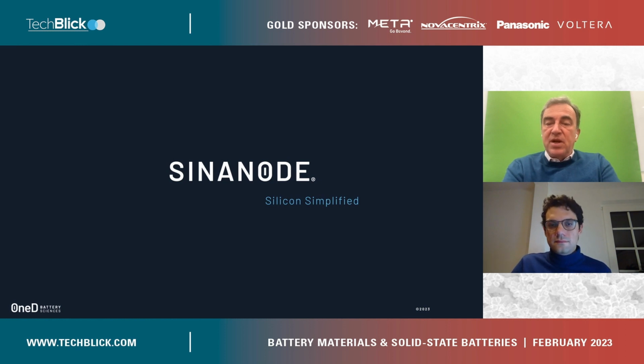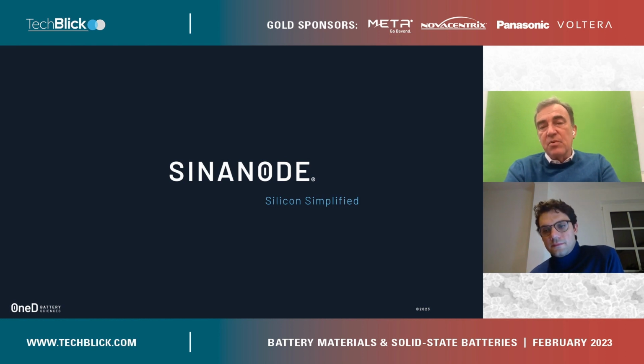The other way that we increase stability is that we make experimental anode electrodes in which we have two layers. The layer with a very high silicon content is directly on top of the current collector. And then on top of that, we put a second layer of lower silicon content and bigger graphite particles that has a greater stability and a greater porosity. This sandwich approach provides an ability to produce high energy density, but also high power density. So we have a number of approaches, and we work to optimize that with each customer.